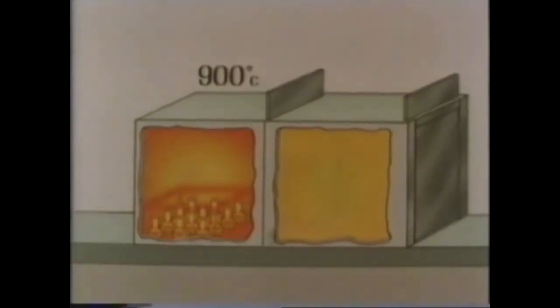of 900 degrees centigrade for carburizing. The carburizing gas here is a mixture of cracked methane and air. The gas is passed over the components, completely covering them for 10 hours. The case is then carburized to a depth of 1 millimeter, and the surface now contains 0.8% carbon. The original material contained 0.1% carbon throughout.